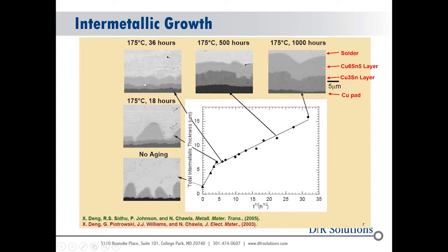So that kind of slows it down, makes it a little bit more robust. But as I grow that layer thicker and thicker, now I've got this very uniform intermetallic structure where the crack can just zip right through it and break. So that's one reason, at least one of my theories. In fact, one of my colleagues at the University of Maryland came up with that theory. Now why, there's a large difference in strength when you have a very thick intermetallic versus an intermetallic that's very spiky or sort of like a mountain range. The crack cannot propagate without hitting a ductile material.